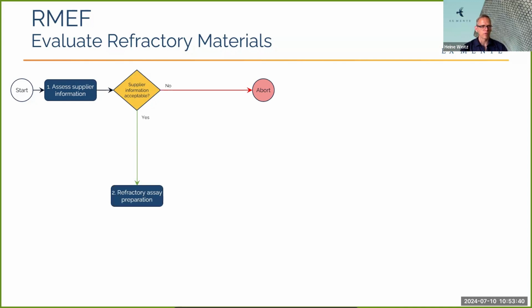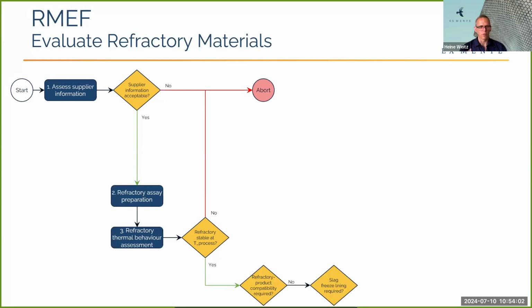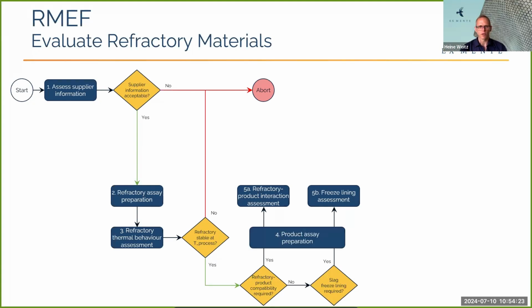Okay. If the supply information is good, you can go to refractory assay preparation, do a thermal behavior assessment, and then, again, you're at a point where you need to do an evaluation: see if the refractory material is stable at the process temperature. If it's not, again you abort, but otherwise you can go on and look at the containment strategy. Do you require the refractory and the product to be compatible? If not, do you require a freeze lining to be formed? And then you can do the appropriate test depending on what containment strategy you have. But before you can look at those assessments, you need to determine what your product assay is.